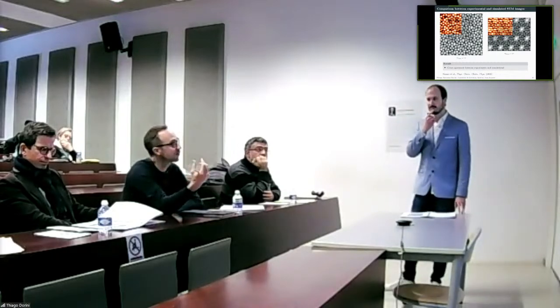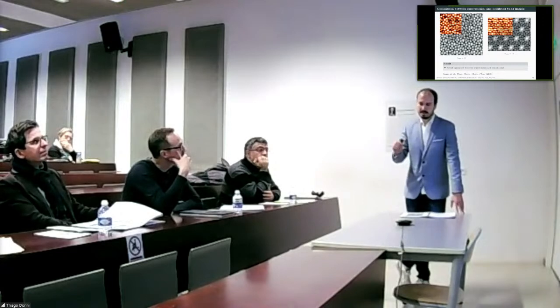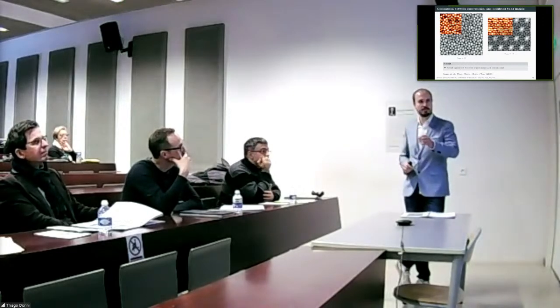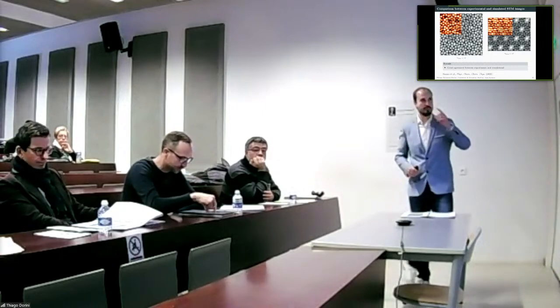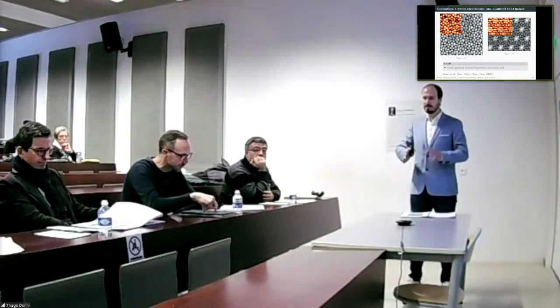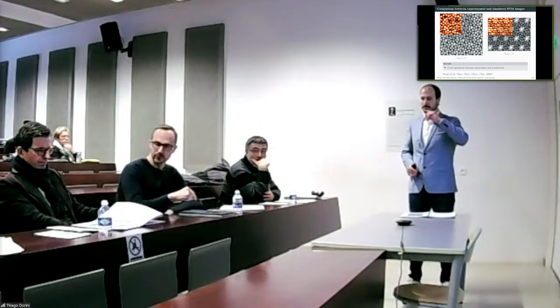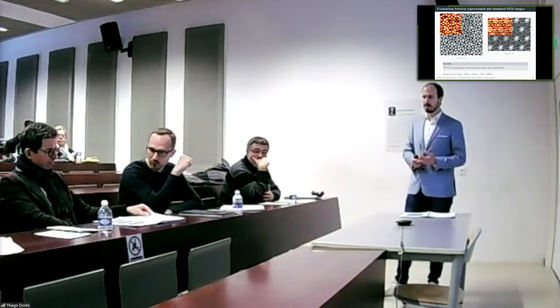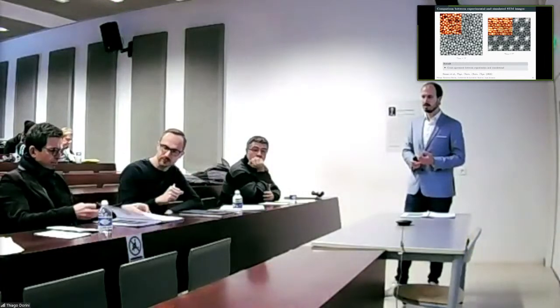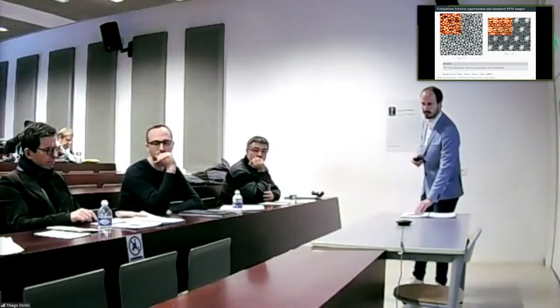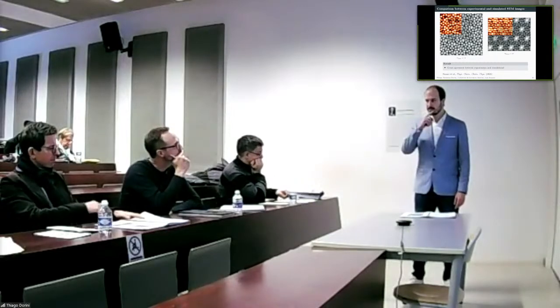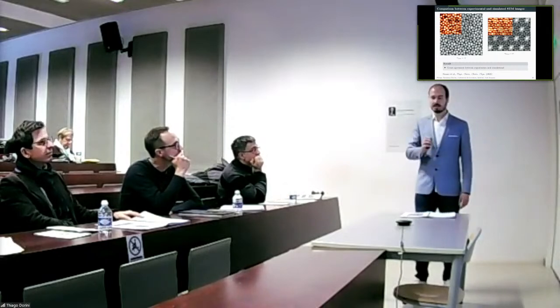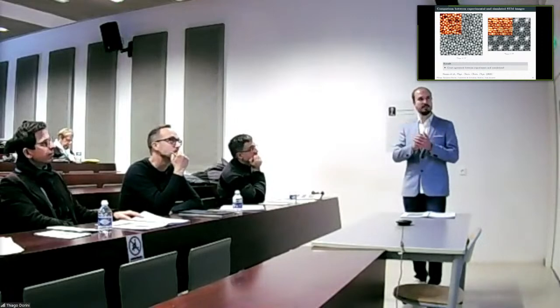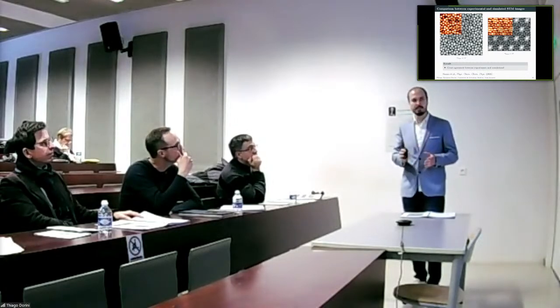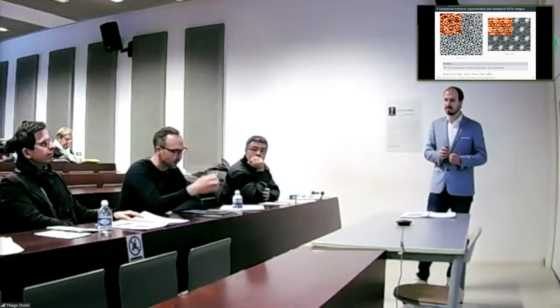Is it the substrate underneath, that these are on top positions on the platinum? Well, this contrast happens only, in this case, I believe it's 1.5 volts for the bias. Yes. So we try to compare exactly with the biases that were applied experimentally. So I'm talking about page 103, in the bottom row. Yes, you have these bright protrusions there. So this only happens at this specific voltage, 1.5. If you go to 0.5, it does not appear. And I tried to look if it's actually the height of this atom, but I'm not quite sure why it is right on that spot specifically for this voltage.